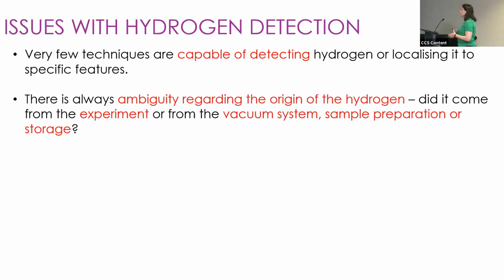Furthermore, there's always a little bit of ambiguity regarding the origin of the hydrogen that we actually detect. Did that hydrogen come from the experiment, the hydrogen that we put in there during charging, for example electrochemical charging, or did it come from the vacuum system? That's particularly important in these high vacuum instruments such as the NanoSIMS. Sample preparation with polishing and grinding in water, for example, or even just storage of these samples: is it picking up hydrogen? So that's where isotopes come into play.